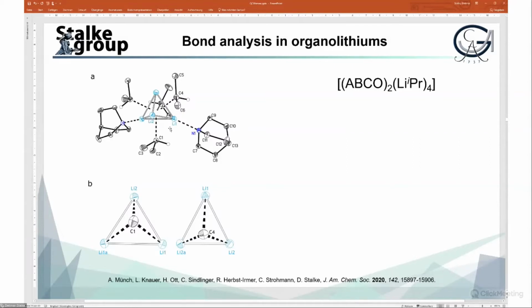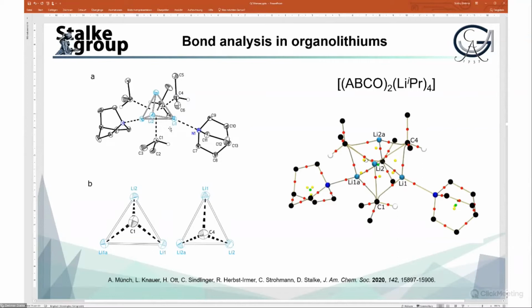If we look at that in the charge density and multipole analysis, then we could find all the bond paths. The bond path comes from the carbon to the 3 lithiums, but there is no bond path between the lithium atoms. So that was the first hint that there is no bonding.